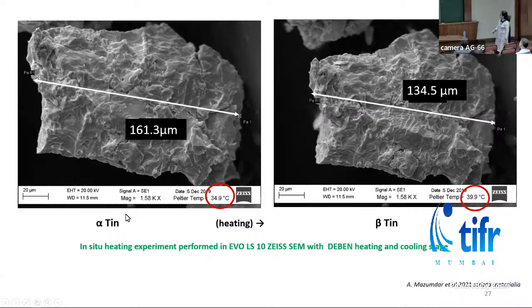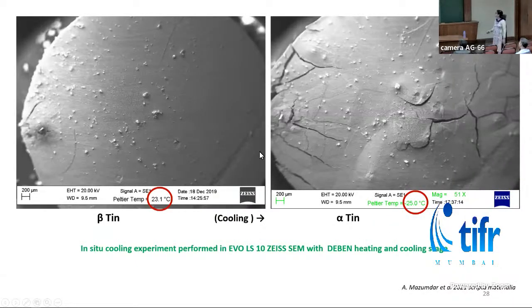So this is an alpha tin sample. At 35 degrees centigrade, we can see the dimension of the sample. When the sample was heated to 40 degrees centigrade, here we could see the reduction in dimension. That means the alpha tin has transformed to beta tin. As I mentioned earlier, beta to alpha tin transition is very slow. So this is a beta tin sample. It was kept in SEM for 2 days at minus 25 degrees centigrade. And here, after 2 days, we could see that there are cracks in the sample. That is because the sample has expanded.